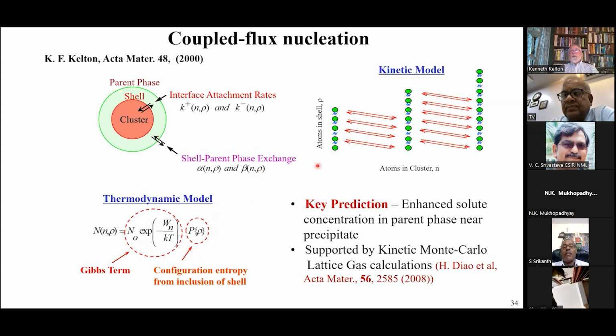That's this term. The kinetic model is a little more complicated because now you have to look at the population not only of the cluster size, but of the number of atoms in the shell region. That's shown here vertically. And so, in other words, you have to have at least one atom in the shell region before you can combine with the cluster to give you a cluster of a larger size. So this staircase kinetic model is characteristic of this.